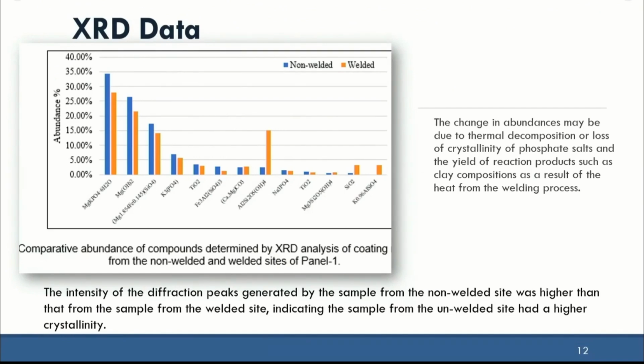Then we identified the heat affected zone, and we went to the back side where the coating is, and we tried to look into the structure of the coating. What happened to the three different areas identified by XRD data? It's a complex structure, so we would like to look at the abundance and occurrence of different components in the coating.